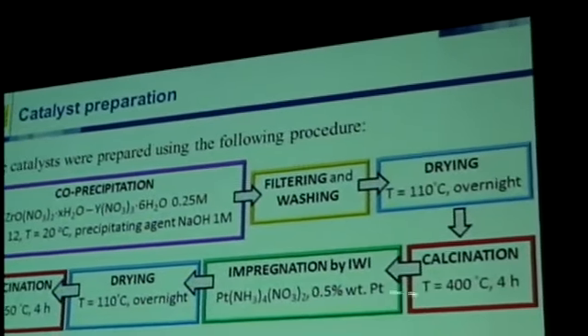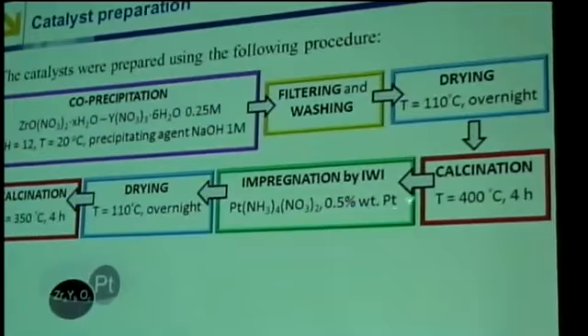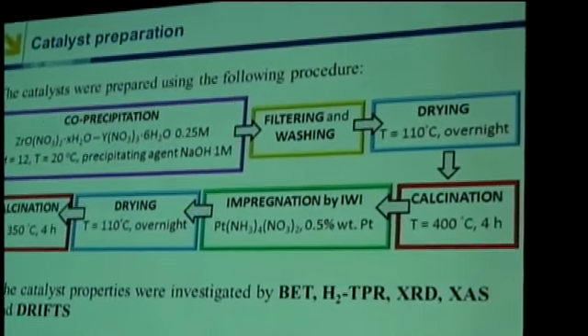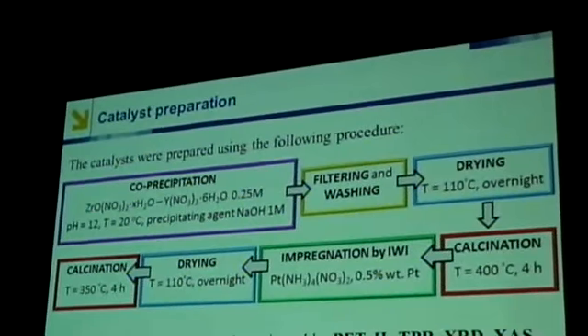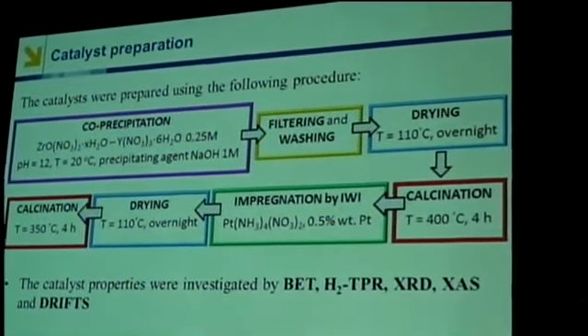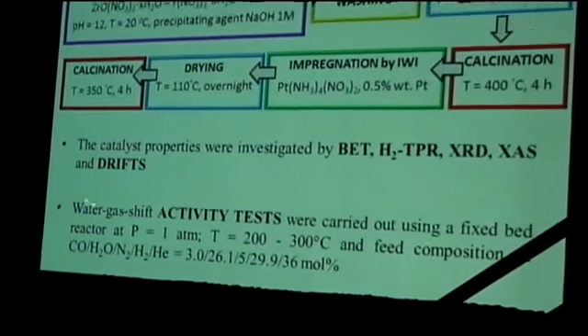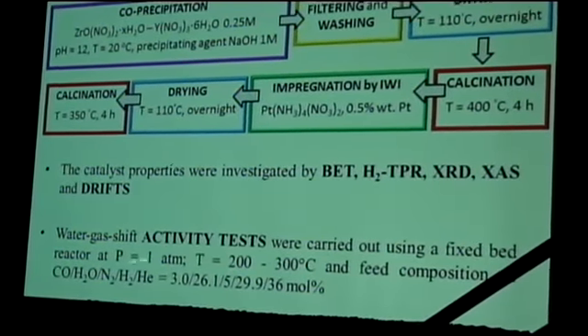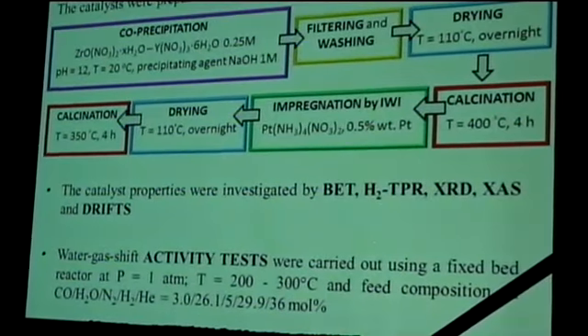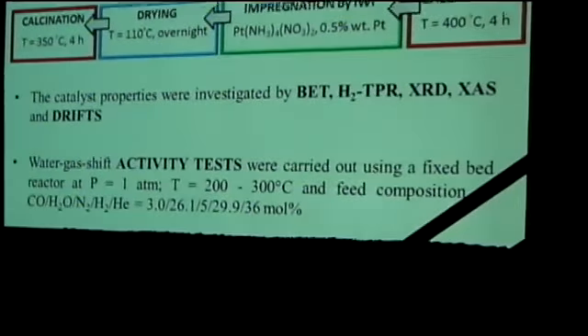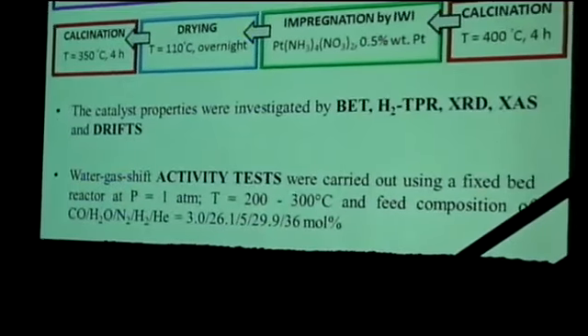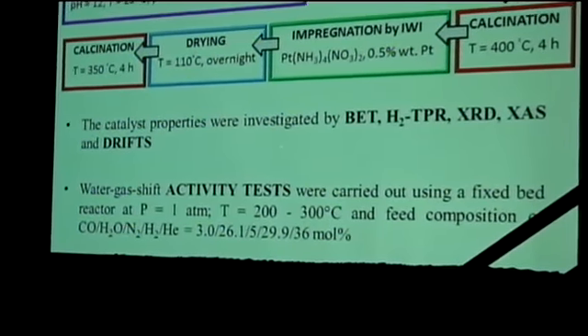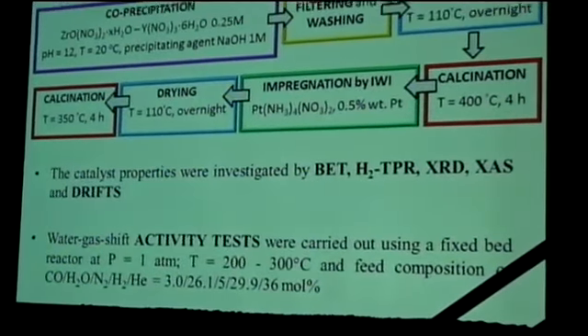And then we added the metal by incipient wetness impregnation using tetraamine platinum(II) nitrate as a salt. Pretty standard preparation method, drying and calcination at slightly lower temperature. And then we investigated the catalytic properties by a number of characterization methods, including X-ray absorption spectroscopy and infrared. And we carried out water gas shift activity tests using a fixed bed reactor under conditions which would mimic the low temperature shift feed for a fuel processor, except we did not include CO2 just for ease of analysis.